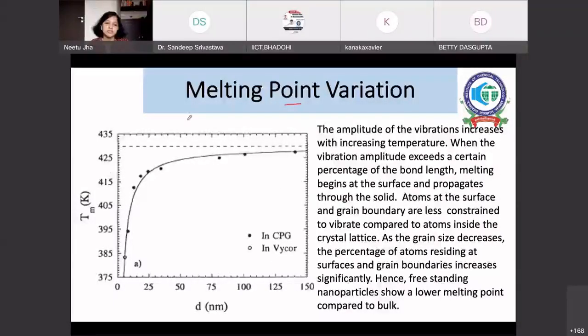So this is an example where we try to see how the melting point of a nanoparticle changes. So the thermal property of a particle, how it changes with size. So if this is the melting point of the bulk material, I'm not talking about a particular material here, because this trend is mostly true for all the nanoparticles, mostly 99%. But again, you might see some exceptions also. So for most nanoparticles, if that is for bulk and you keep on reducing the size, after some time you will see that there is a huge reduction in the melting point. So the melting point reduces with the size.